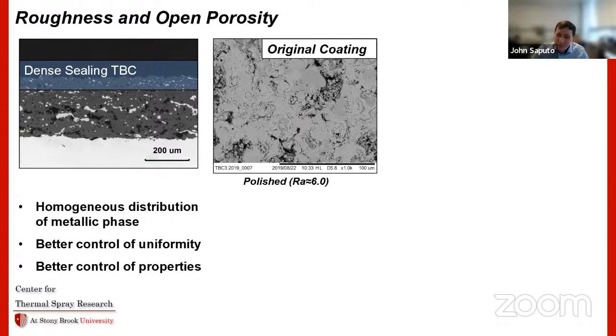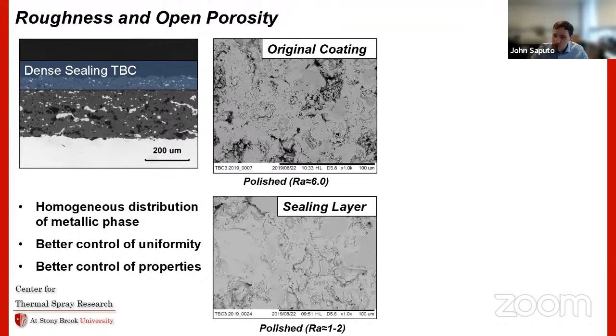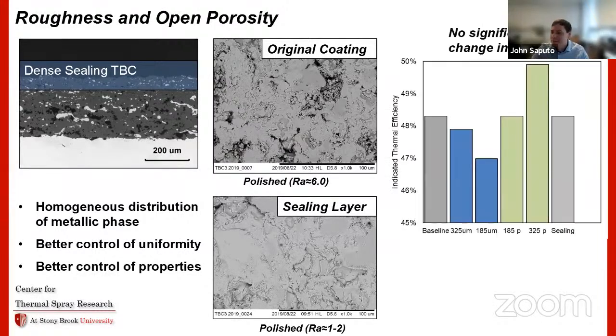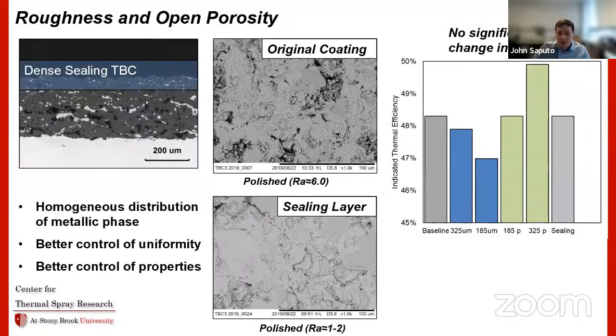So our original coating looks something like that. You have all these big open surface pores, you put the sealing layer on top, and they all go away. Everything looks great, right? Except you do engine performance testing with this, and you see no change in the efficiency, which is kind of interesting. This story is going to get a bit repetitive, and I'm going to say the same thing like 6 times in a row. We've tried a whole bunch of things and seen really similar results. So our thought from this is that we have this dispersed metallic phase inside of this.